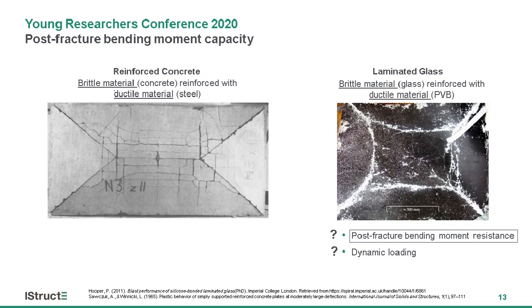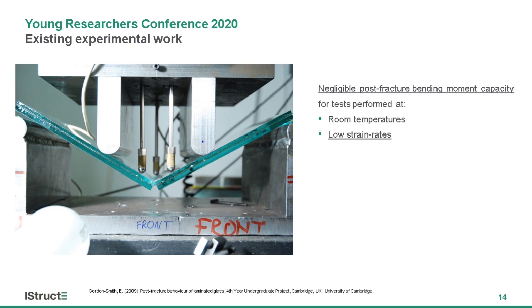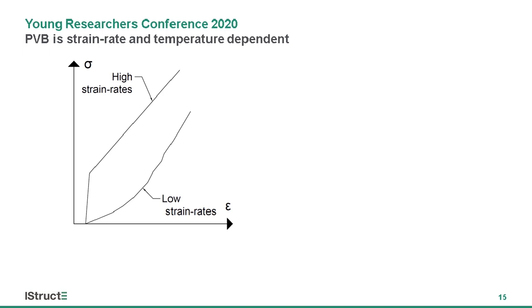Starting with the post-fracture bending moment resistance of laminated glass, previous experimental work on post-fracture specimens has demonstrated that this is negligible. However, these tests were performed at low strain rates as opposed to the high strain rates anticipated under blast loading. This is important as PVB is a thermoplastic polymer that becomes significantly stiffer at high strain rates. The response under blast loading is therefore fundamentally different compared to the previous experimental work at low strain rates.